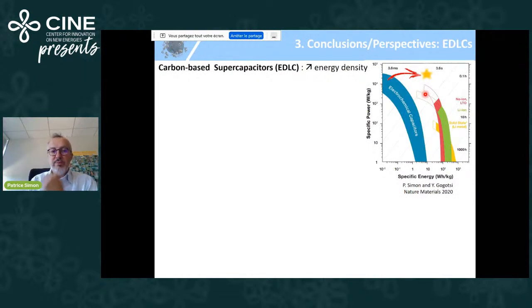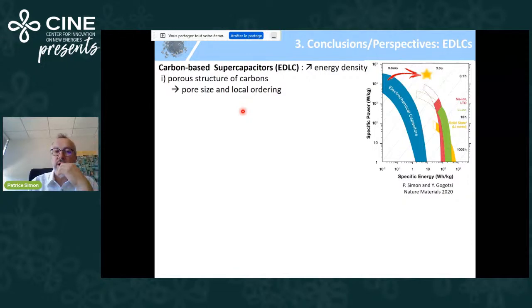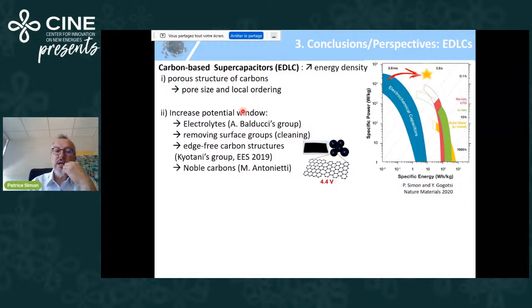And now for the conclusion and perspective, I would say that for the carbon-based supercaps, the goal is to increase the energy density. And you can do it by controlling the pore size and the local structure ordering of the carbon, as I mentioned before. I gave examples. But there are also very interesting works in the literature. You can work on electrolytes, this is André Balducci, to design more stable electrolytes with larger delta E. You can clean the carbon from surface groups. This is already efficient in the companies, with Maxwell and Tesla proposing 3-volt cells.